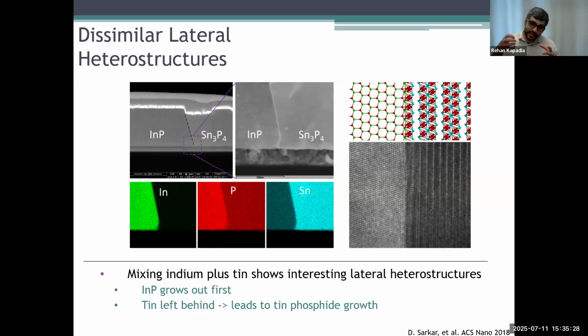Now, the thing is, the tin phosphide doesn't nucleate off the indium phosphide. It nucleates somewhere else, and then it just grows, and the two crystals just meet and form this interface, instead of what you would normally do when you're growing vertically, where you start with one fully formed crystal and you come in and add an atom at a time. And so any strain issues, which are the key thing that causes big problems in this area, get mitigated because you're forming the crystal separately. And so then they almost zipper together, but they zipper together in a different way than you would normally expect. That was very unexpected for us, and it's something that we'll come back to when I'm talking about the heteroepitaxial growth.